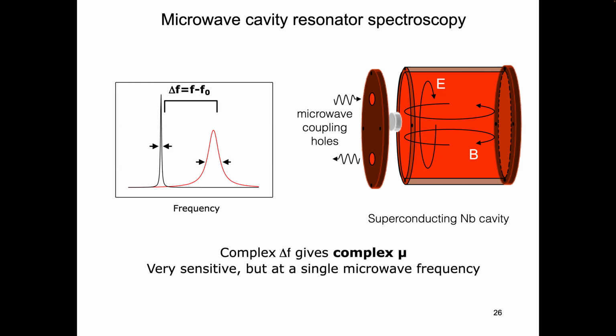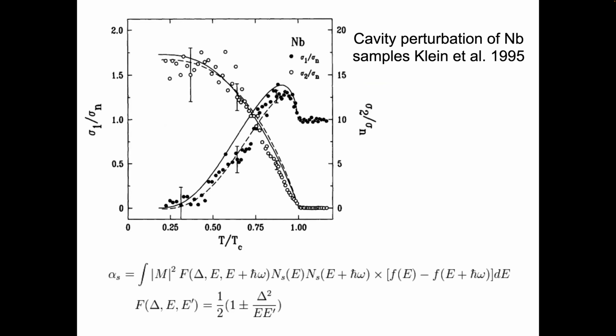This is a classic experiment here on niobium, which is a conventional BCS superconductor. And so that's how this experiment was done. And remarkably, this is done by so-called cavity perturbation. A small bit of niobium was placed into a cavity. The frequency shift and the broadening is measured. And from that, you can measure the real and the imaginary parts of the conductivity. The imaginary part of the conductivity is generally proportional to superfluid density. It just kind of comes up almost like an order parameter.